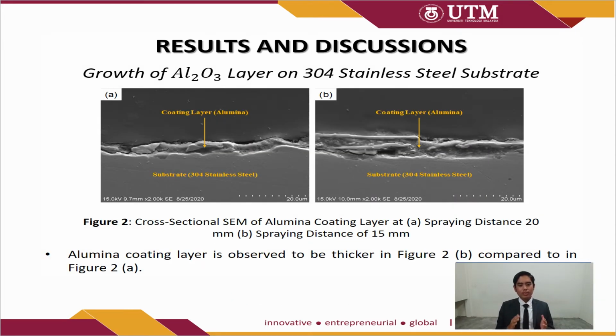In terms of results and discussions, first of all, we will take a look into the growth of the aluminium oxide layer on the 304 stainless steel substrate. As we can observe, figure 2A represents the cross-sectional SEM of the alumina coating layer at a spraying distance of 20 mm, while figure 2B represents the cross-sectional SEM of the alumina coating layer at a spraying distance of 15 mm.